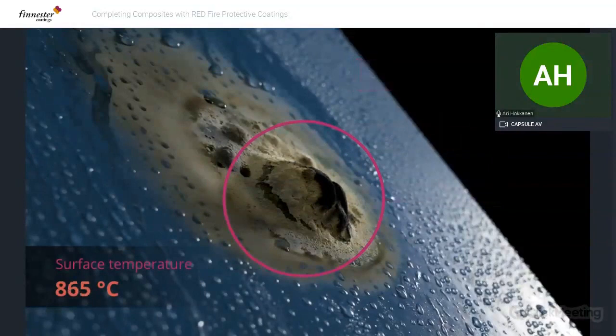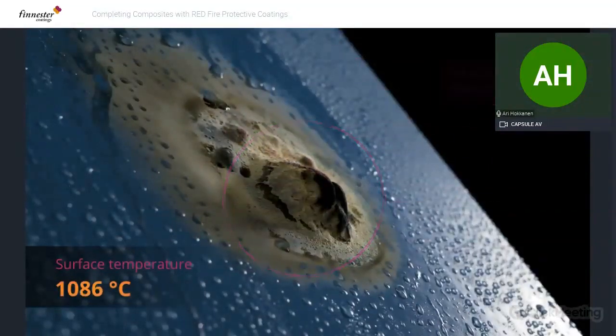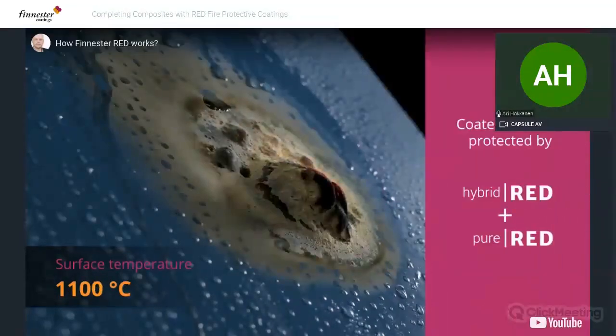Here we go again. Organic burns away, ceramic bubble is formed, and ceramification is complete. And this is now stable. You can burn it, hours and hours in 1,000 degrees, and that's stable. And that stable ceramic bubble will isolate the heat from the composite itself. So the heat will never go to the composite, and that's why you can have that standard composite in your process.